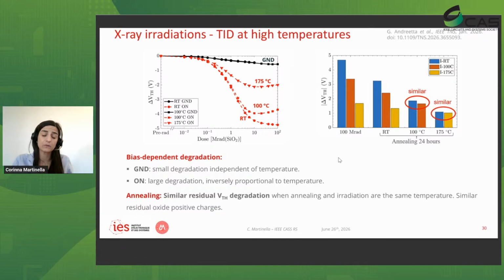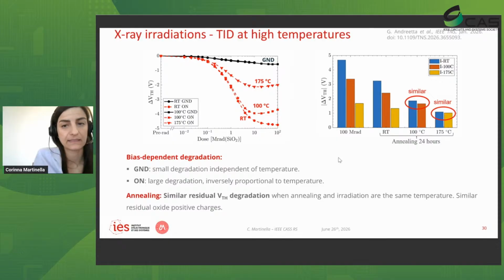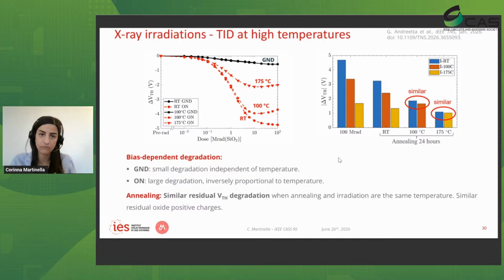So overall, we concluded that independently of whether the device was exposed at that temperature or annealed at that temperature, the residual degradation was observed to be very similar. And so the temperature there was really the key factor that allowed the recovery of the damage induced by the total ionizing dose.